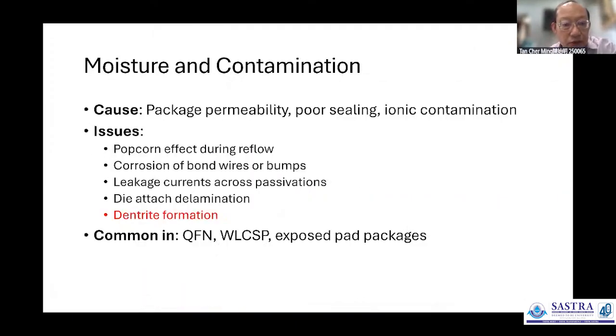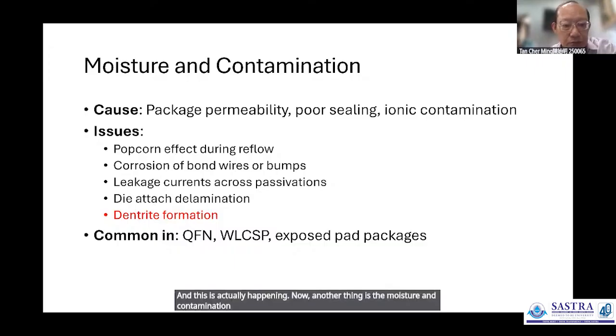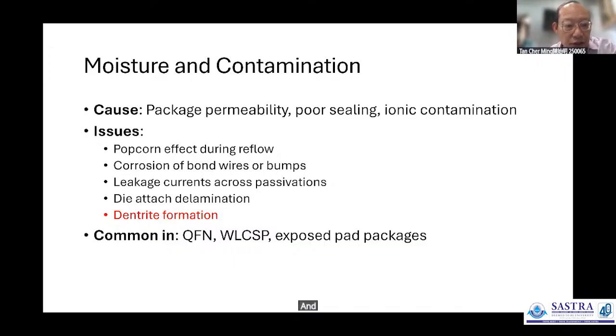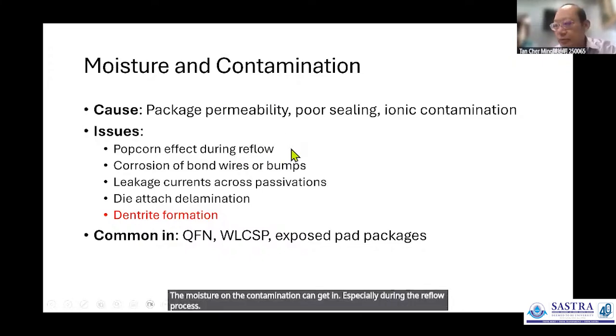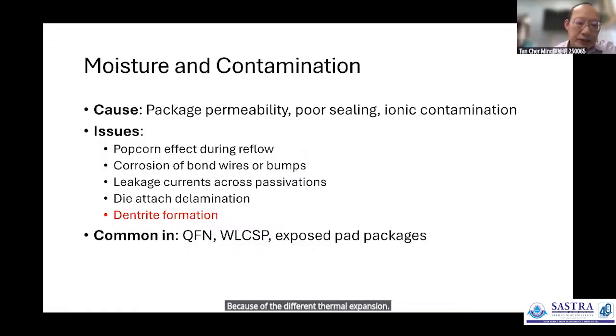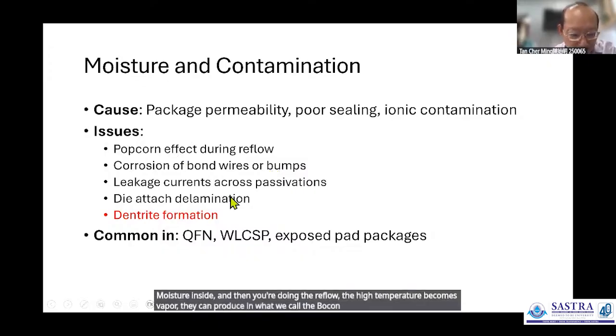Now, another thing is moisture and contamination. Packages are supposed to protect the die from moisture and contamination. But if your sealing is no good, the moisture or the contamination can get in, especially during the reflow process. Because of the different thermal expansion, there will be some gaps, and moisture can go in. Also, if the package itself or the PCB itself has some moisture inside, then during the reflow the high temperature turns it into vapor, and it can produce what we call the popcorn effect.